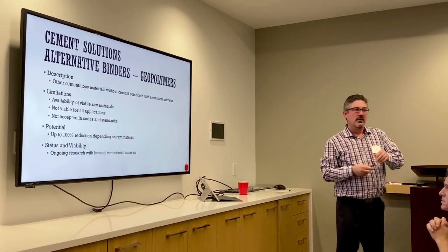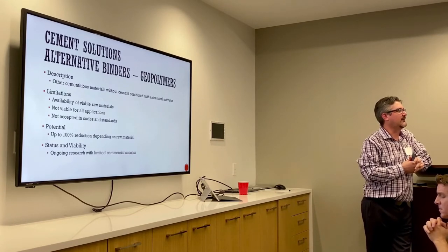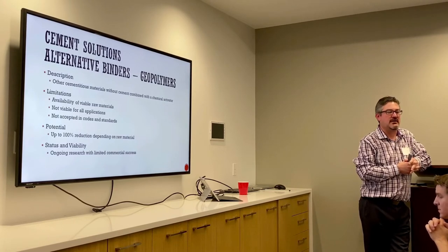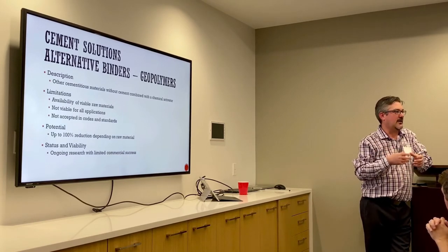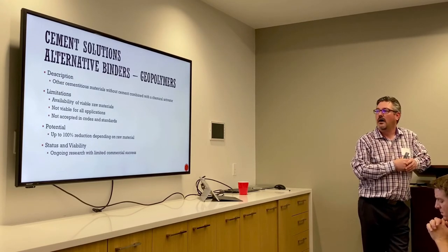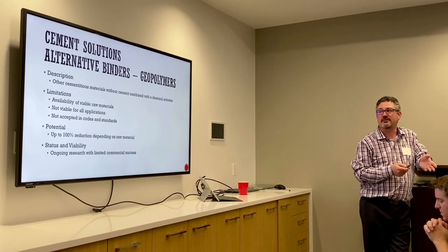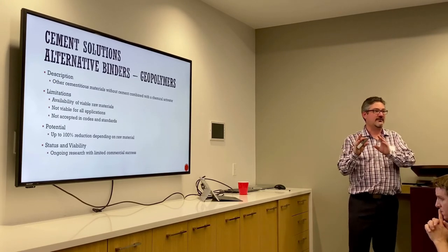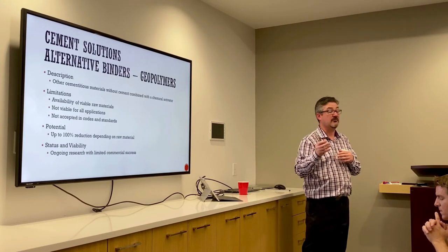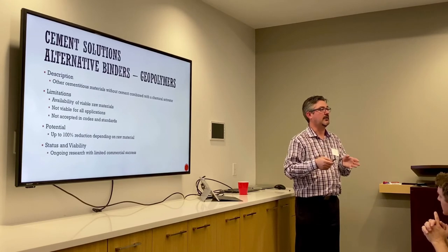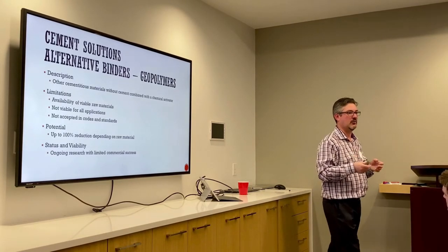Has some potential there. Now, some people in the industry would have heard about this material called geopolymers. This is basically cement-like materials that don't have cement in them. So some of these can be considered carbon neutral depending on what the material is. They use a chemical activator to make them go hard, so they work kind of like cement, but they're not cement. Their availability depends on what raw materials are available. They're not viable for all applications. They're not accepted in codes and standards, so the use is somewhat sketchy in some cases. Depending on what the material is, there could be 100% reduction in comparison to CO2 emissions from cement manufacturing, but it's really ongoing research at this point, and there have been attempts to make this commercially viable, but most of those companies have wound up in one way or another.